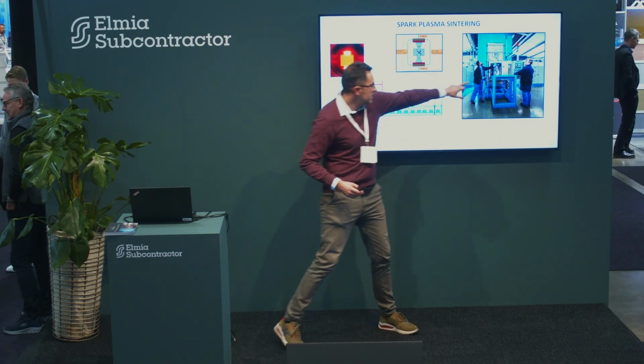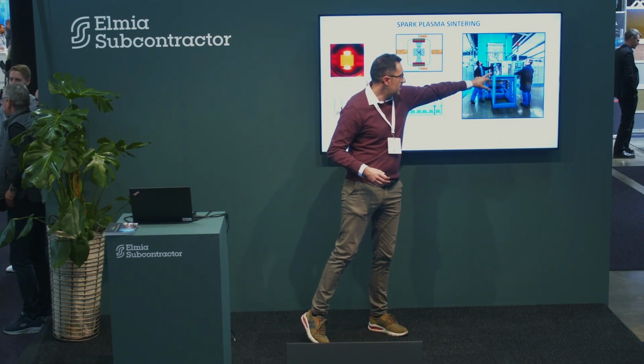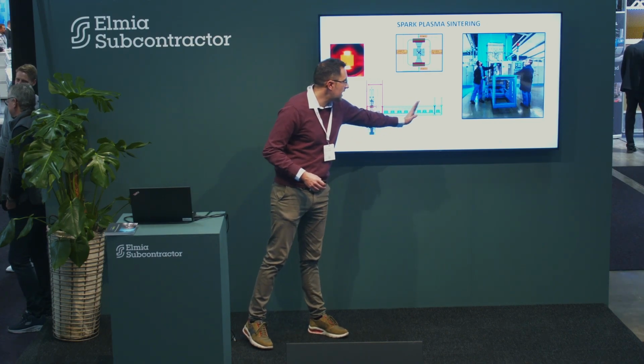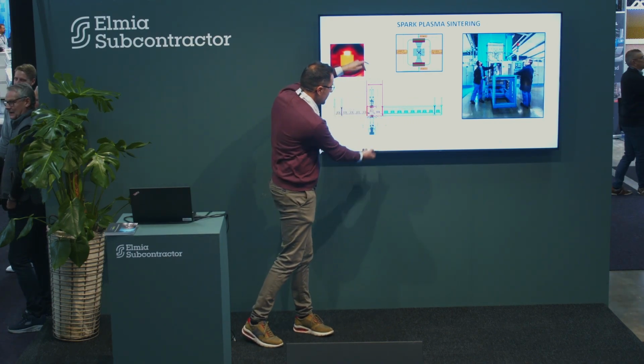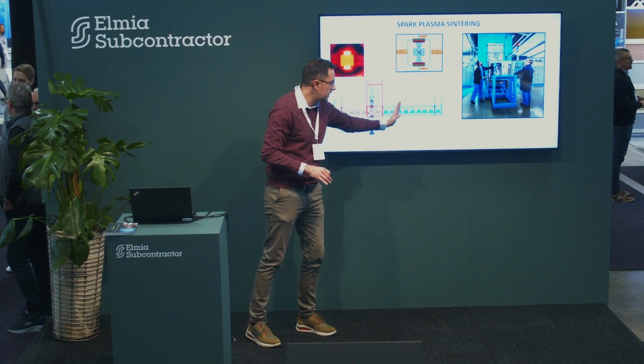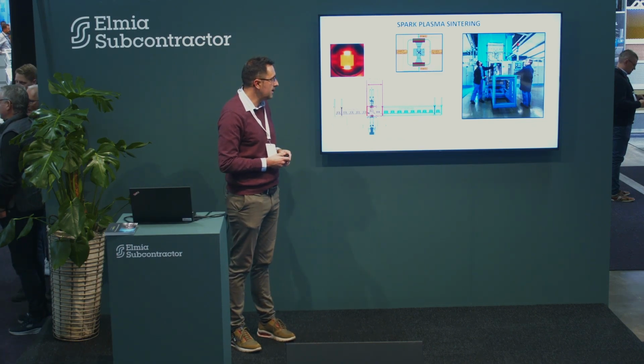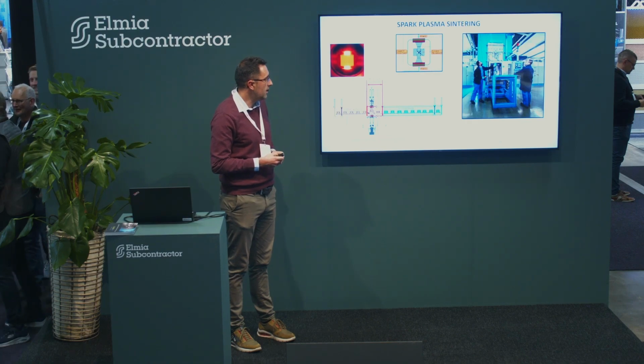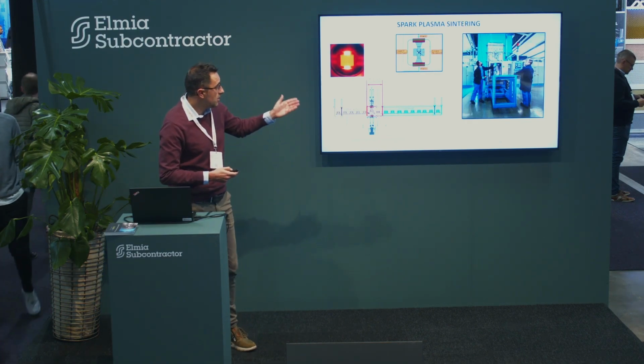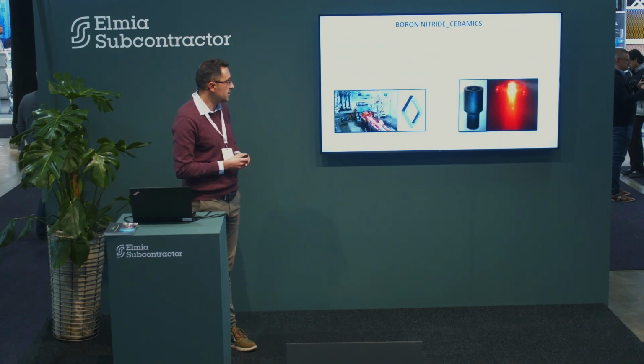This is a mold inside the machine. You can sinter the material only inside the mold, but if you put a preheating channel and a cooling channel, you just preheat, then you make the pressure and final heat in just 10, 15 minutes needed, and then you cool down. So you can produce one part every 10 or 15 minutes in a ceramics, which is really very, very, let's say, impressive. So with this technology, we produce more materials of the families that I described before.